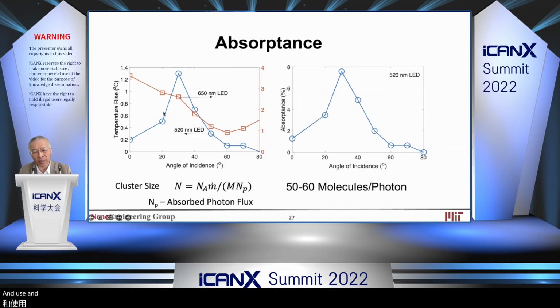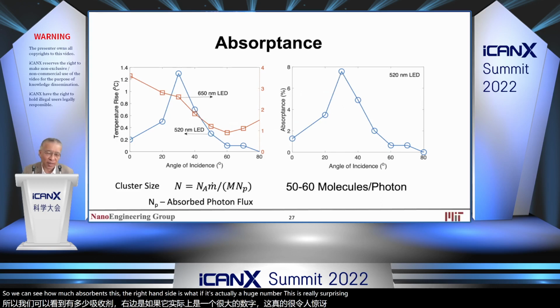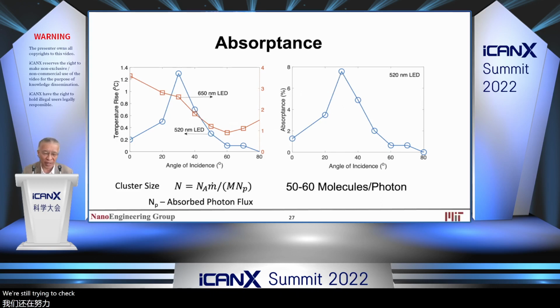And the red is the thermal evaporation, so we can see how much absorptance. The right-hand side is what they infer. It's actually a huge number. This is really surprising, and we're still trying to check, okay? But using this, we can calculate that one photon can excite 50 to 60 molecules. This is almost 9 times more efficient than thermal evaporation.